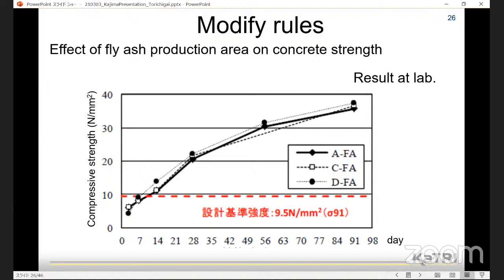This slide shows an example of confirming the compressive strength of dam concrete using fly ash A to D. This test was done at the laboratory. The concrete used was the outer part concrete of the dam. It was found that the type of fly ash used this time does not significantly affect the compressive strength of dam concrete. Based on the test result, the dam was constructed with changing the production area of fly ash in consultation with the ordering party.